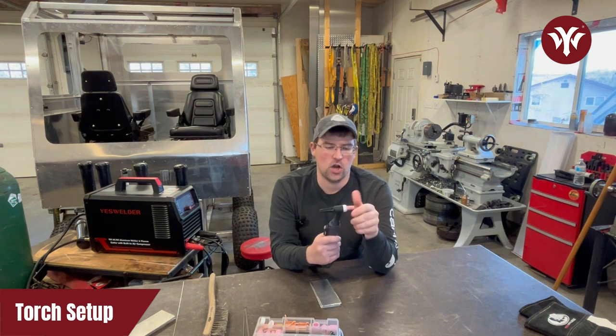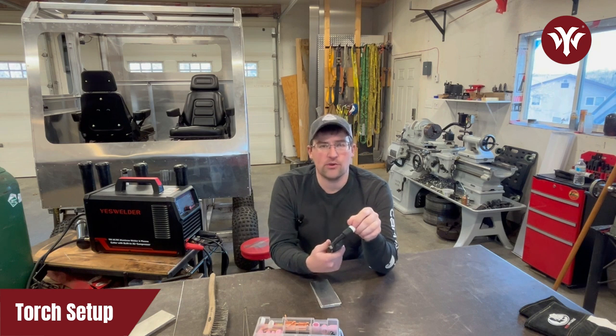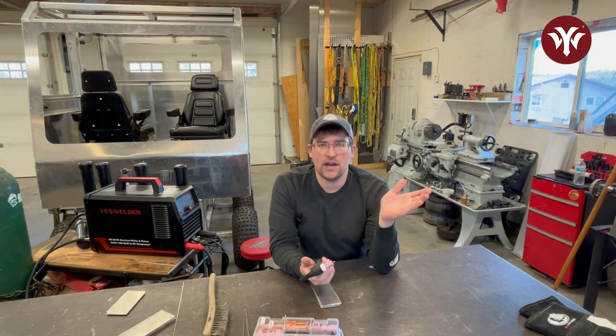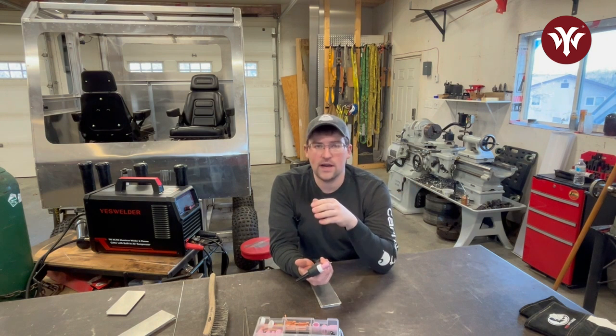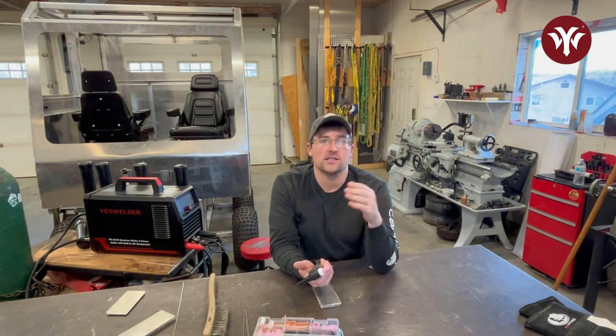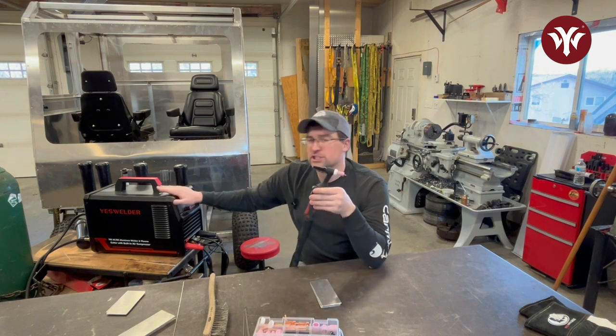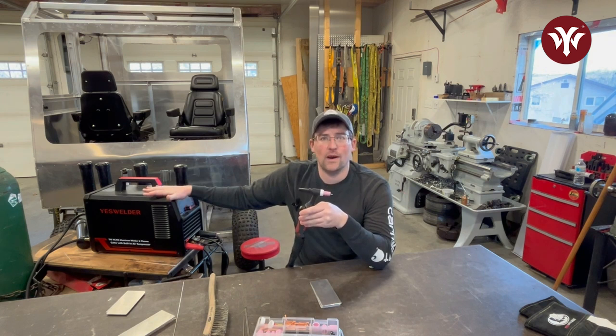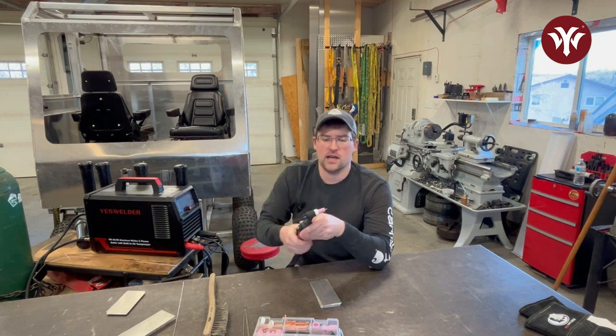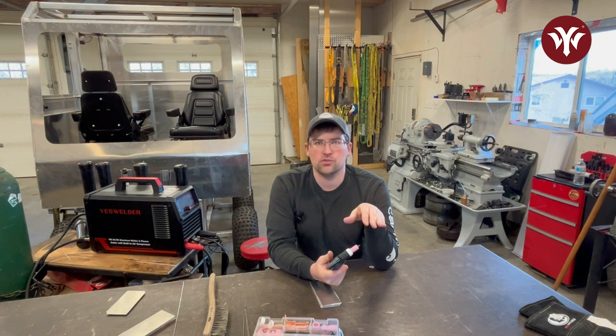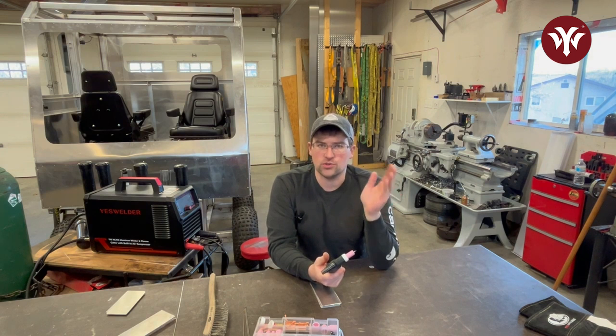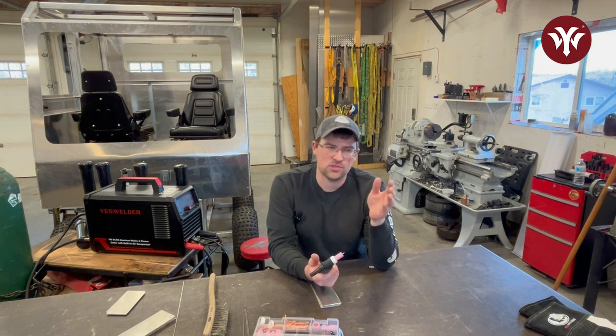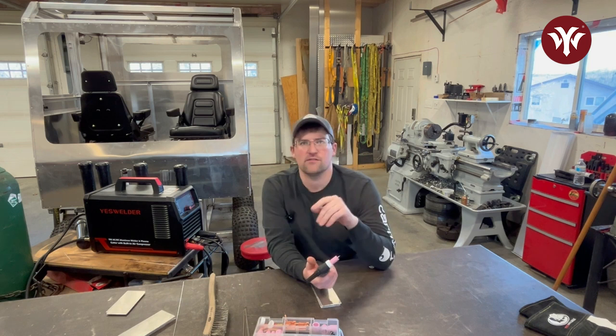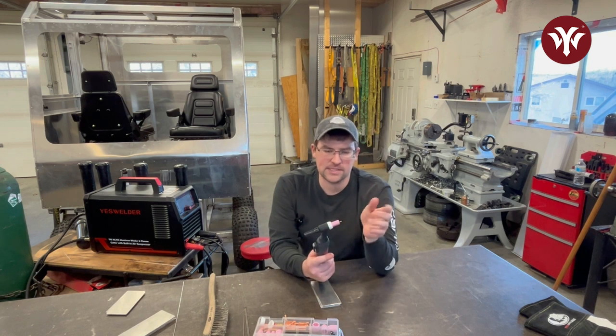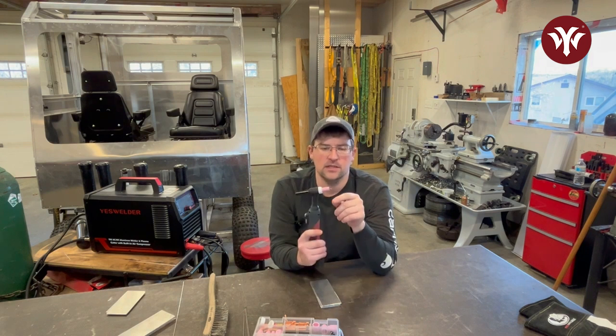The next part is the size of tungsten you're using. So today we're going to be using a 3/32 tungsten. You can get them in a variety of sizes, 1/16 of an inch, 3/32, 1/8, and generally the larger tungsten has a higher current carrying capacity. But for a machine like this, I really doubt you'd ever need to go to a 1/8. That would be the top end of that size. 3/32 is what I primarily do most of my welding with. I don't often go too thin. I usually stay within about 1/8 to 1/4 inch material, sometimes 3/8, and sometimes 1/16 of an inch or a little thinner. But like I said, today we're going to be using a 3/32 lanthanated tungsten.